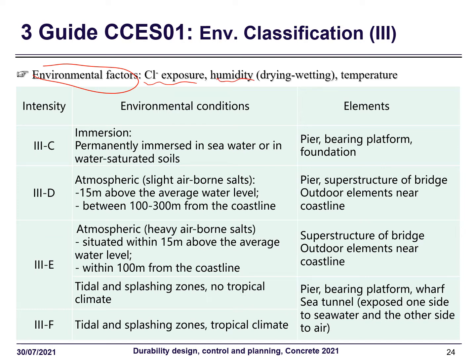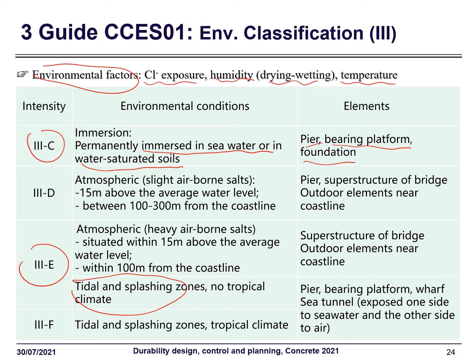So on the basis of this analysis, we look at the environmental factors, including the chloride exposure condition, humidity condition, including drying and wetting, and temperature. For example, for immersion, permanently immersed in seawater or water-saturated soils, we treat it as the lowest grade. It's the III-C. It applies to a pier or bearing platform or foundation immersed in water, because in this exposure there is very little oxygen to support the continuous corrosion. On the contrary, if we have exposure to tidal splash and run, we have much higher intensity. In the tropical climate plus the splash and run zone, we attribute the highest intensity III-F.